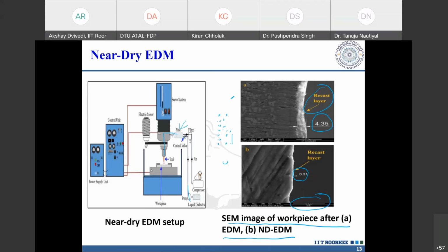Now, in this particular case, when you compare the recast layer with near dry EDM and conventional EDM, you can see there is a phenomenal difference in the amount of recast layer that comes. Here you have a recast layer which is only 0.31, very less. End result, you have better surface quality. In fact, the integrity of the machined surface with near dry EDM is far better than a conventional one.